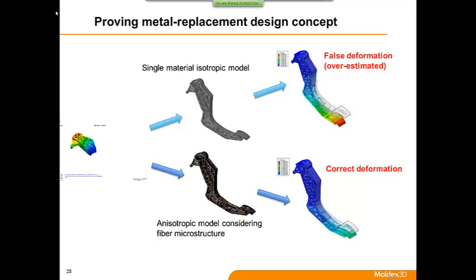So actually for this part, it's already strong enough. Because you see on the bottom part, this part is injected, the melt enters from left to the right. So a lot of fibers are oriented following the flow direction. So it will make the part stronger after you press it. But if you don't consider that, you will think the part is isotropic. So during the prediction of the structural simulation, the deformation is actually higher. So if you think it's higher, you may increase the thickness and you may increase the rib structure.